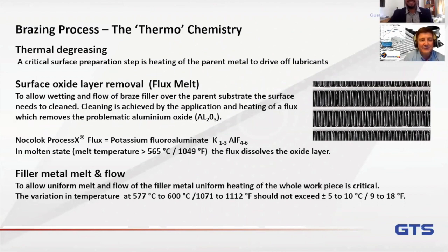So if we take that list of seven things that are important in brazing, we've identified that three of them are temperature related. In the manufacturing process of brazing, the first major step is to perform what we call thermal degreasing. That's obviously to take any hydrocarbons or lubricants that may be poisoning the surface of the product itself. Because if that stays in when the actual brazing process occurs, that's going to cause some contamination of the process itself. Probably the most important thing, though, is the use of the flux, as I alluded to before.